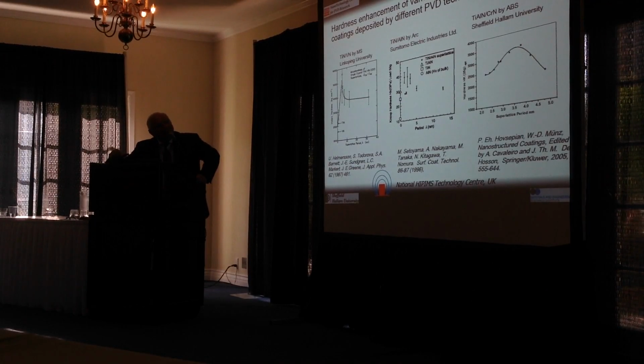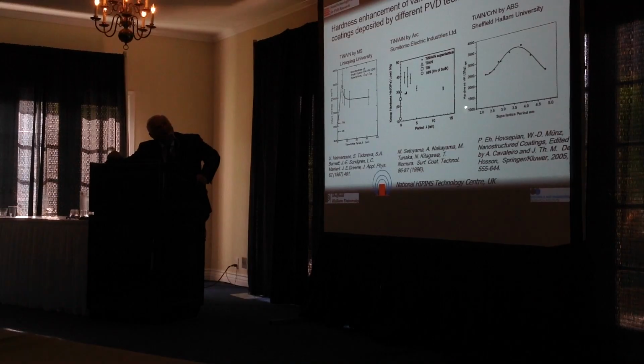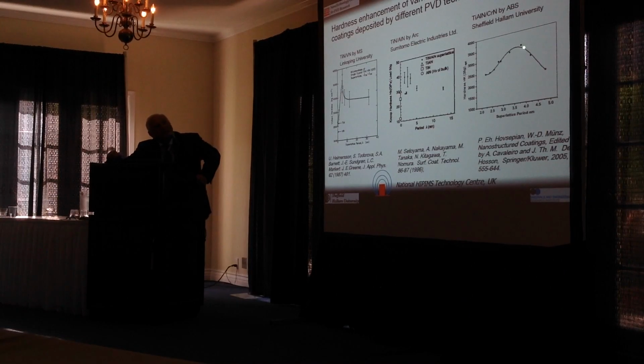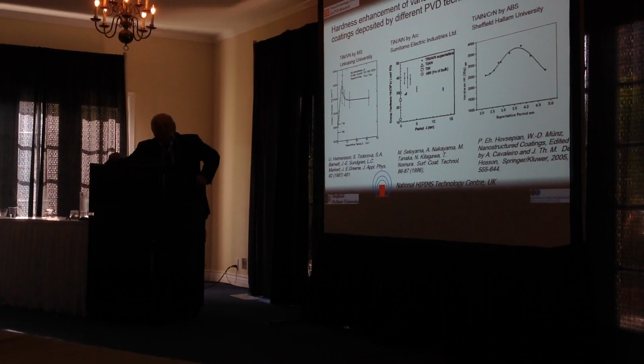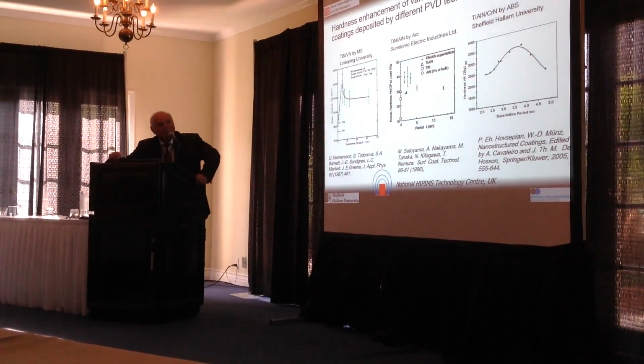The Japanese guys were a little bit more modest. They said that, of course, there is a hardness enhancement in a specific bilayer thickness range, but it is in the range of 40-45 gigapascal. We found similar hardness enhancement in our research. But still, it is important to know that in a specific bilayer thickness range, you really get hardness enhancement. So this was not a false claim, I would say.